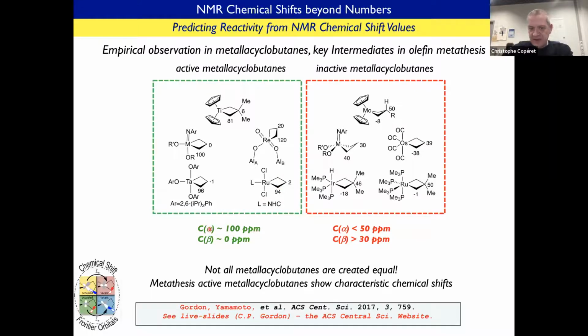So the alpha carbon is highly deshielded at around 100 ppm, and the beta carbon is very shielded. Whereas all metallacyclobutanes that do not contribute to this reaction have rather shielded or similar chemical shifts, whether you have the alpha and beta carbon. So it seems that very simple solution NMR can distinguish what can be a catalyst and what cannot be a catalyst.